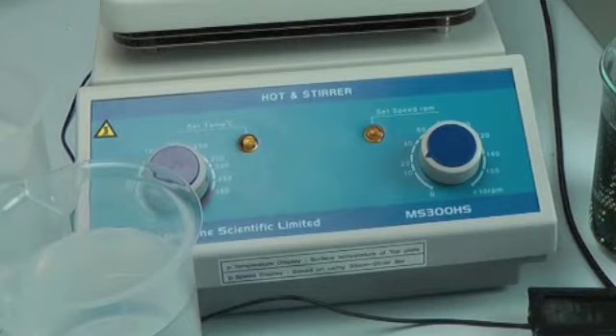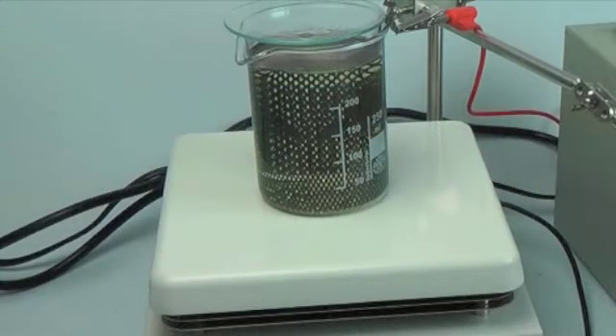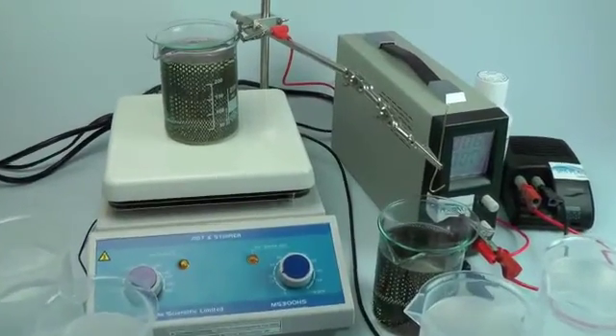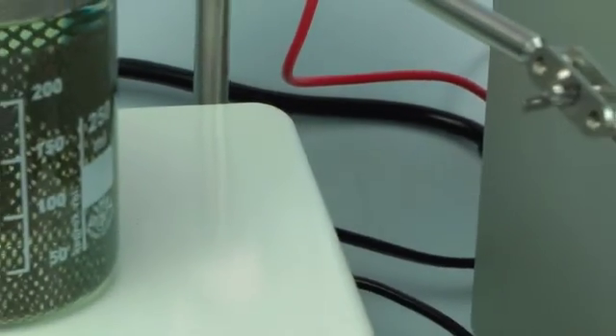Heat the solution to between 48 to 52 degrees centigrade and set the stir to very low, with the mini stirring bar in the palladium tank plating solution. After setting up your palladium tank plating kit, you'll need to work out how long to plate to achieve your desired thickness of palladium.